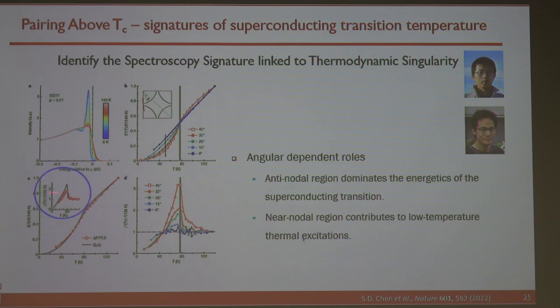So now we can say how we actually can use photoemission to get this image. We know the spectral weight at zero frequency gives you the singularity. The singularity there gives you the phase transition. Then you say, boy, this is a very expensive way to measure specific heat, right? So is the data consistent? Yes, exactly the same. The solid line is the specific heat measurement, the dot is the photoemission. The answer is yes, it's expensive, but we also measure tremendous insight.